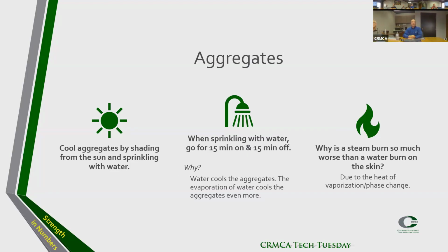Aggregates: cool the aggregates by shading them from the sun and sprinkling them with water. One suggestion that we have is, don't have your sprinkler on 24/7 on the aggregates. How about sprinkling them for 15 minutes on, 15 minutes off, 30 minutes on, then off? It's really a trial. Why? Once you stop sprinkling your aggregate pile, the water starts evaporating from the aggregates.